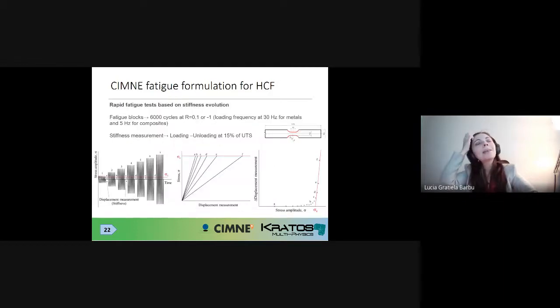Okay, now something else that's very interesting for the high cycle fatigue domain. High cycle fatigue has quite a big problem regarding the experimental time needed to have a full characterization of a material. You need to do a lot of experimental tests. Basically, for each SN curve, you need about 19 specimens if you want to be scrupulous and also have statistical effects accounted for. And this takes a long time. Specifically, for high cycle fatigue, which has lives of millions of cycles, you need about 2 weeks to a month of a testing machine doing these tests. It's completely blocked for that material and that specific geometry.